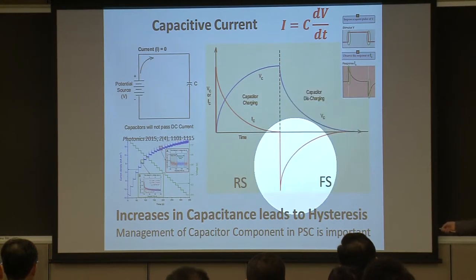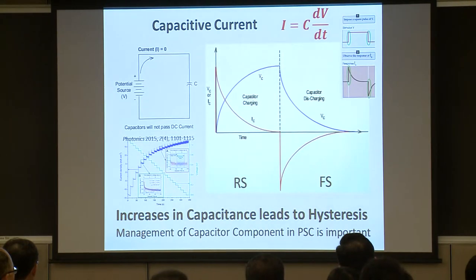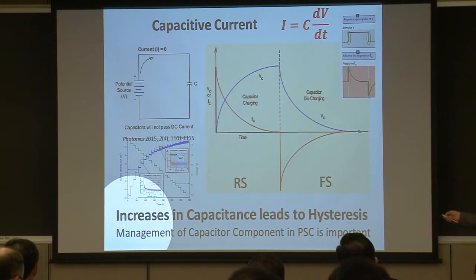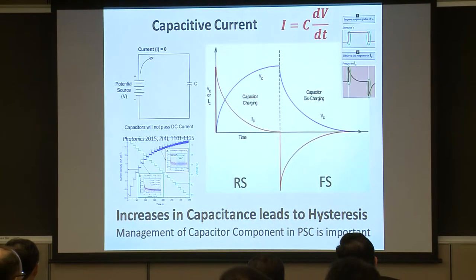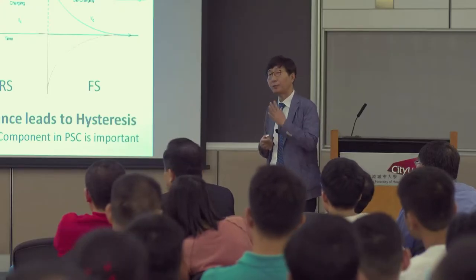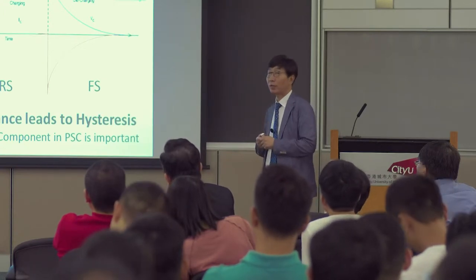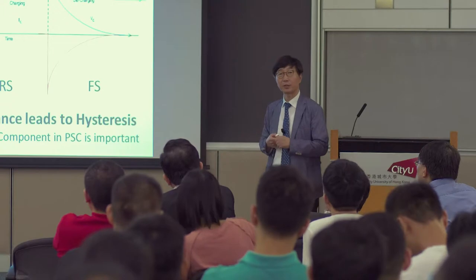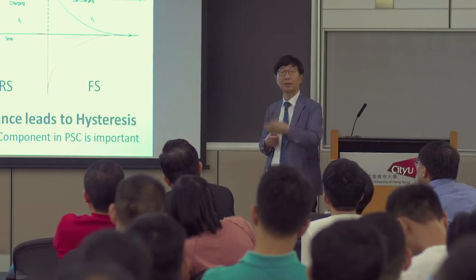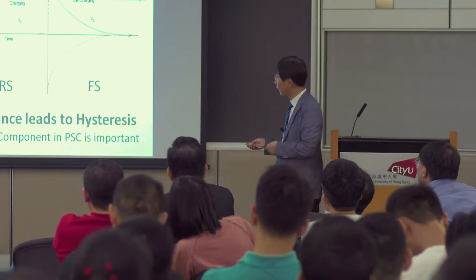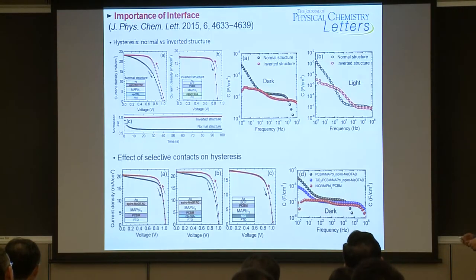Anyway, the charging profile looks like the reverse scan, and the discharging profile looks like the forward scan. So this is due to capacitance. Therefore, if you increase the capacitance, then probably you increase the hysteresis. Therefore, you have to control the capacitance of this perovskite solar cell. So where does the capacitance occur, at the interface or in the bulk perovskite? We have to find out the origins.